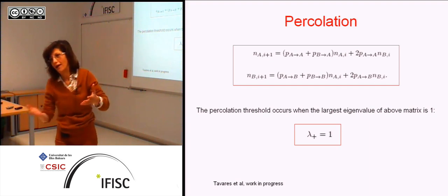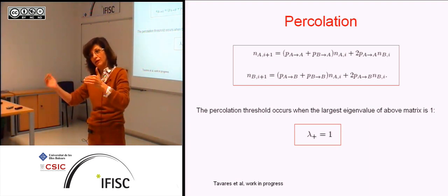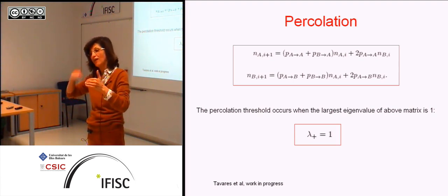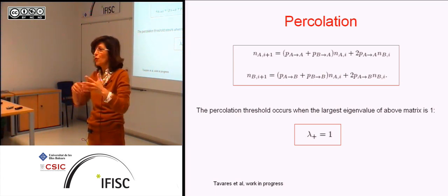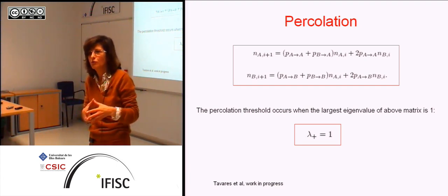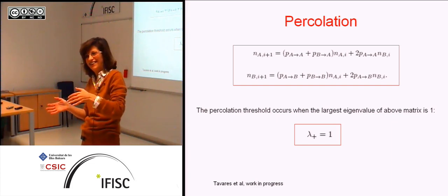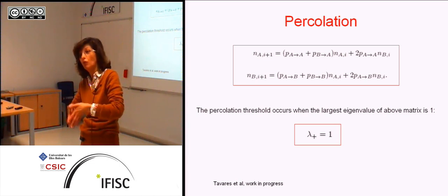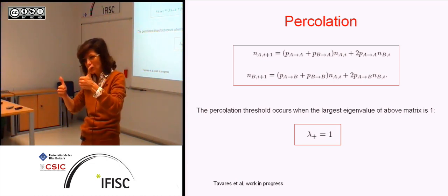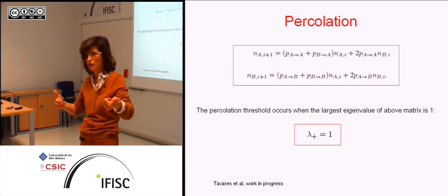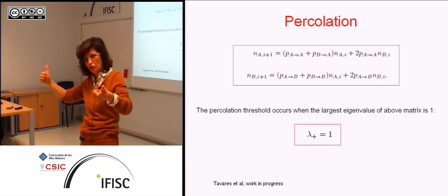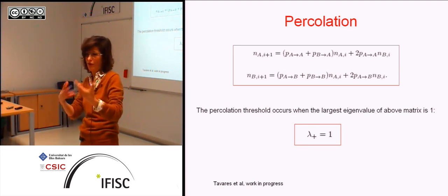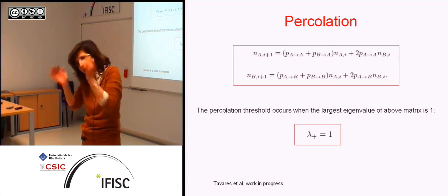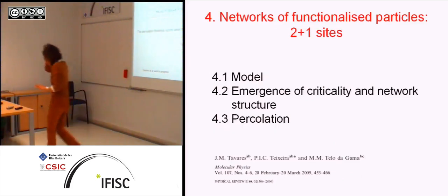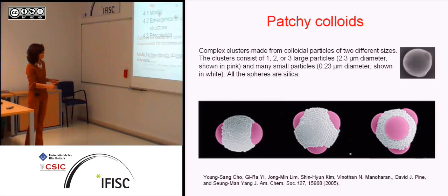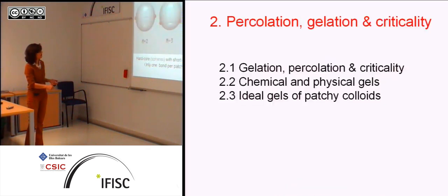So the result is we get a functionality which is non-integer. We preserve the percolation threshold because that comes from the second moment. The model is exact at percolation. And so we then use Flory's result. Well, Flory's has some factorials and so on, but we know how to do the continuation, get Gamma functions and so on. So we can actually write the distribution functions in terms of this effective functionality, which is non-integer, and this probability that comes from matching the moments of the real distribution, which we can calculate without knowing the distribution, to the moments of the distribution with equal sites with this non-integer functionality. And it's exact at percolation, and that's the surprise, it describes the non-percolated phase almost exactly. Of course, in the percolated phase we have problems.